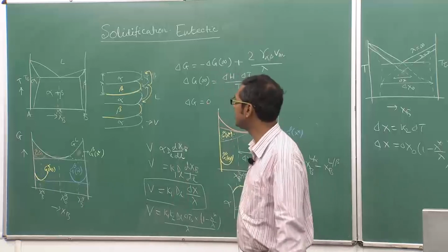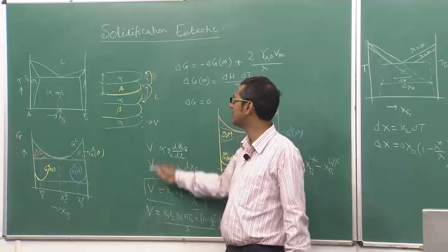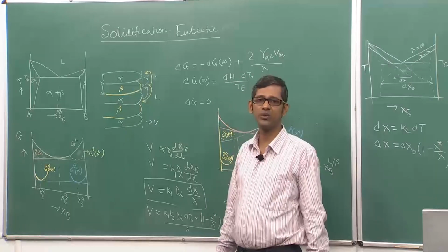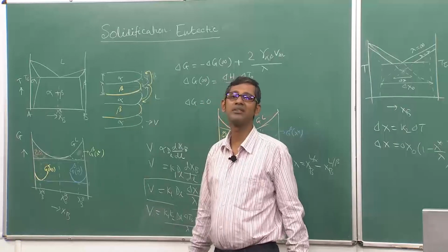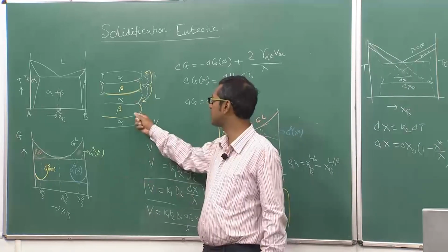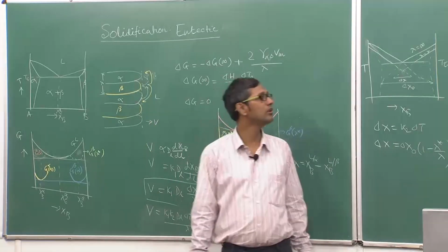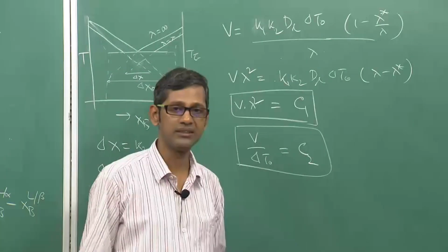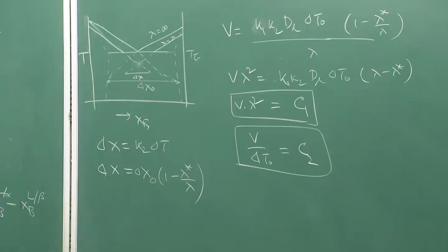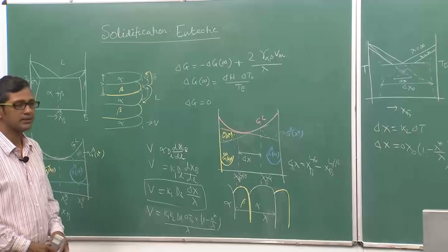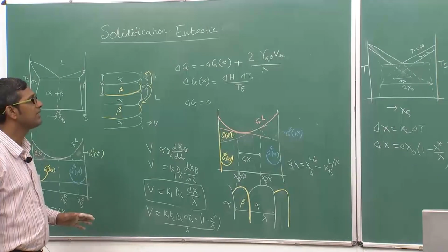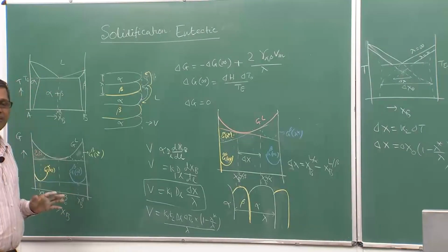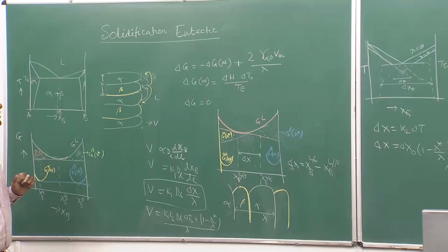A better method is to take a system in which we can actually observe the eutectic growing at a certain velocity. We can observe these lamellae, measure the value of lambda perfectly while it is in contact with the liquid, and use that value at a particular level of undercooling to calculate v. So finally, it boils down to the important aspect that eutectic growth is still not a fully solved problem. It is an undetermined problem in the solidification literature.